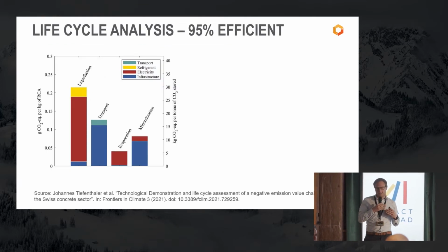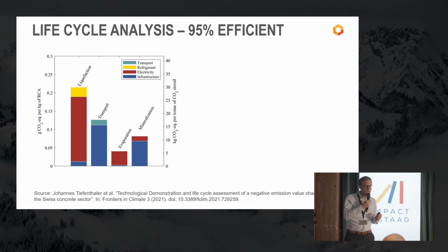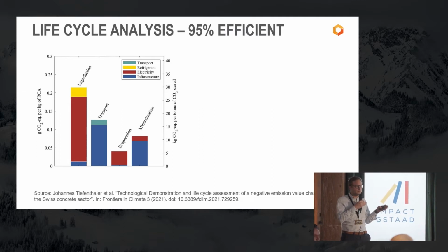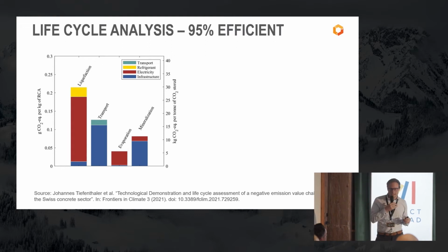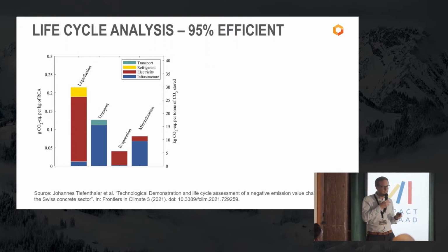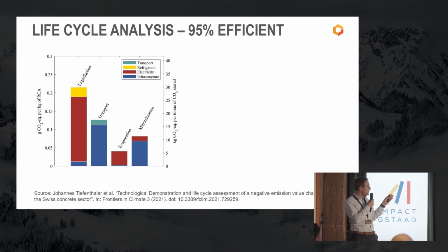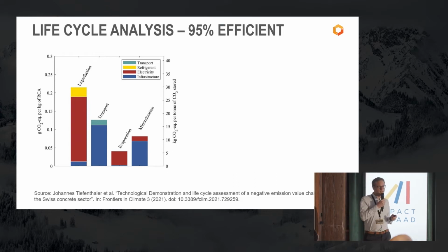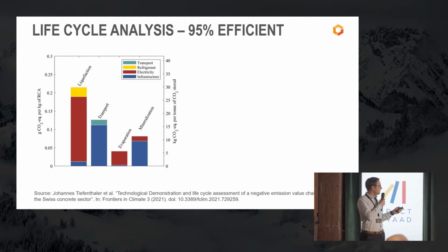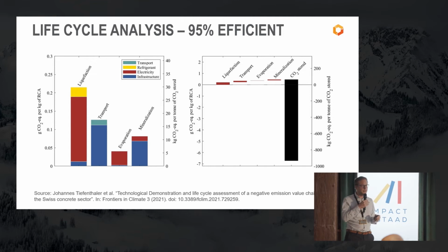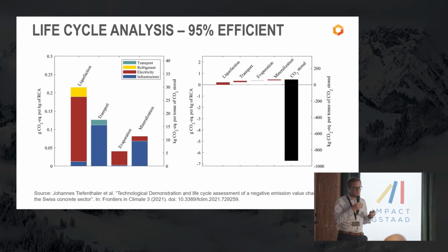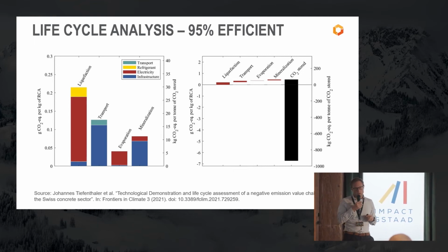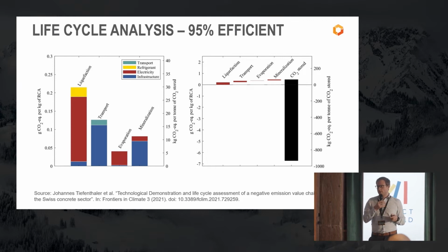In addition, we also assessed the net environmental impact of the chain. And this is important because basically every processing step requires energy and materials, and in today's world that corresponds to an environmental impact. In our case, the additional steps are CO2 liquefaction, transport, evaporation, and mineralization, and they require basically energy, which is red, and steel, which is blue. But if we sum up these impacts for a Swiss case in Bern, what happens is that we emit about 50 kilograms of CO2 while storing 1 ton of CO2, meaning that we have a net efficiency of about 95%.